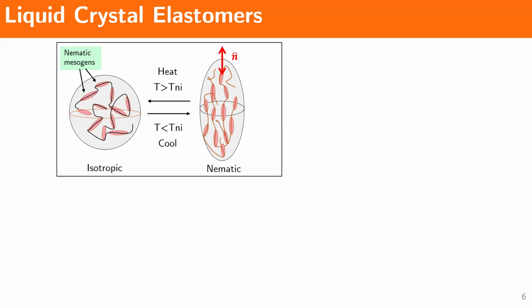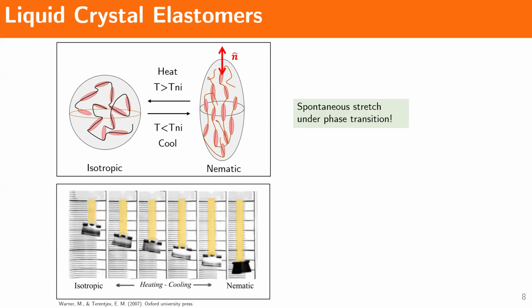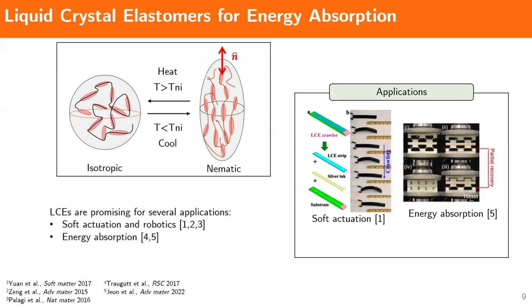But when you cool it down below a certain transition temperature, these mesogens can rotate and reorient towards a preferential direction, called n here, which is also called our director orientation. So you have this disordered to ordered phase transition that happens as you cool down with temperature. As you're cooling it down, the mesogens rotate and reorient, and they bring their polymer chains with them. So often what you will see is a spontaneous stretch under this phase transition when you cool down these materials. This large spontaneous stretch, which is also reversible because it's associated with the phase transition, is attractive for several engineering applications. People have looked into these materials for soft actuation or energy absorption purposes, for example.